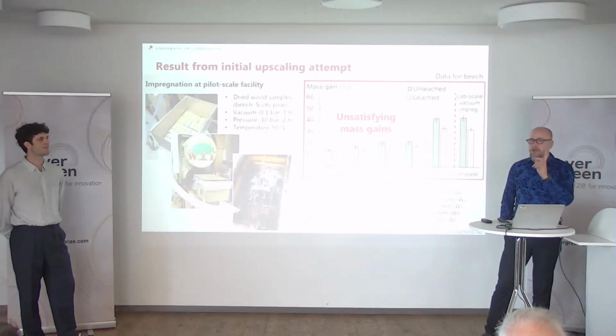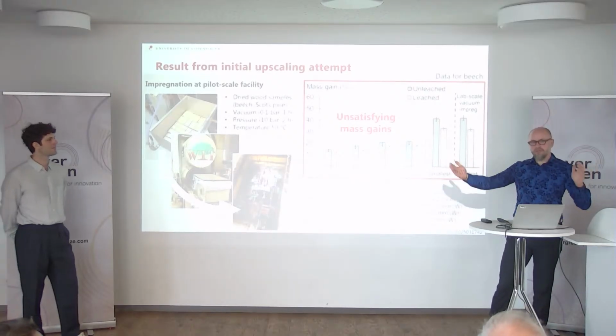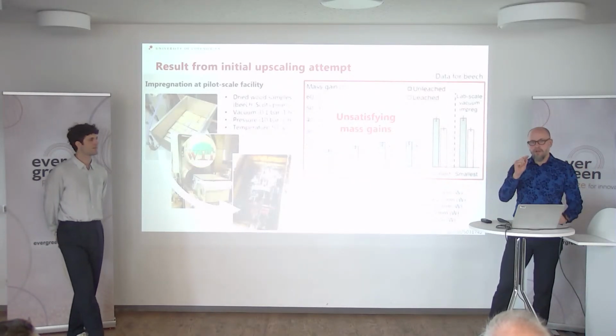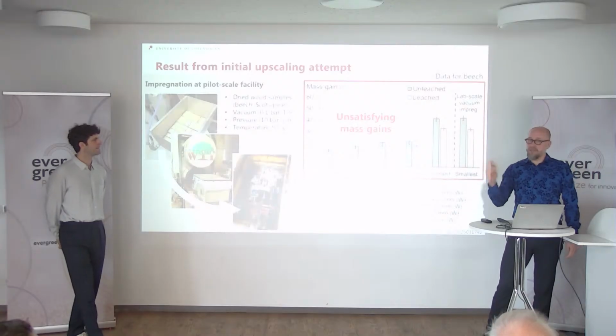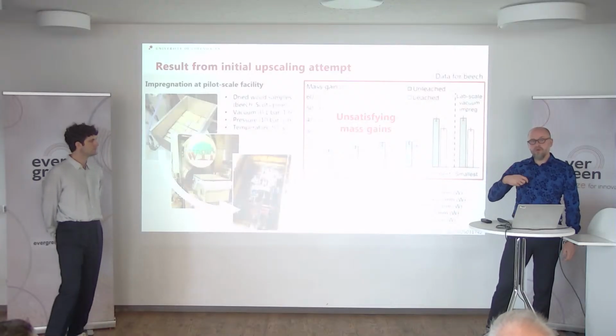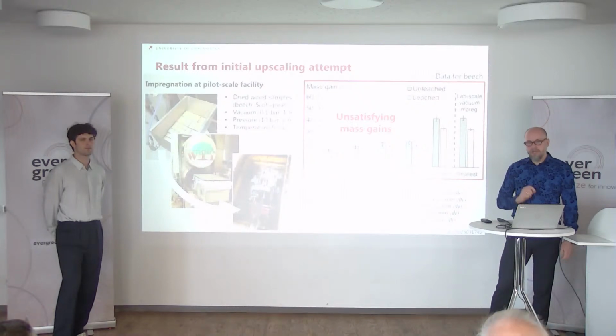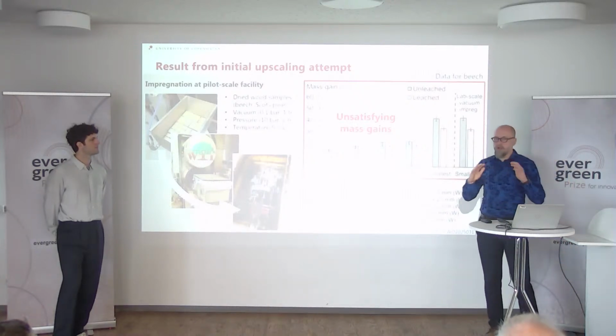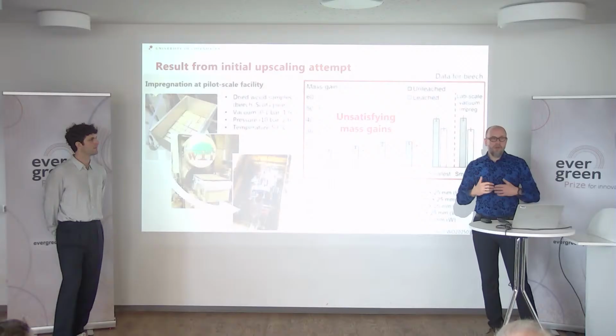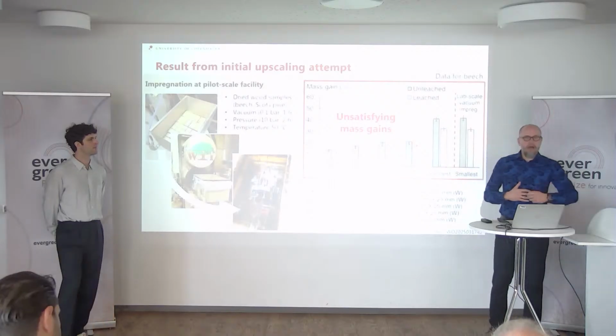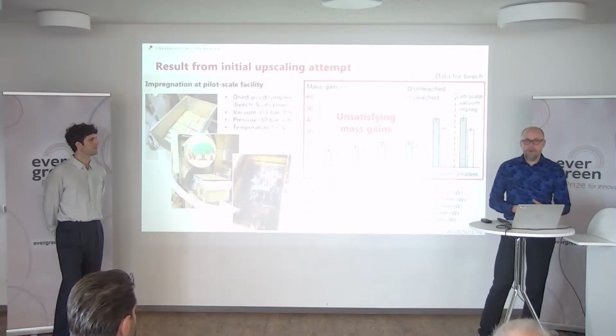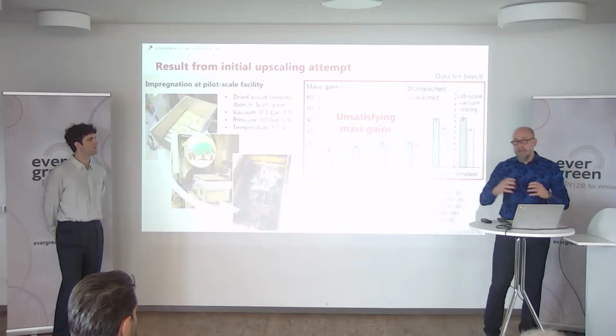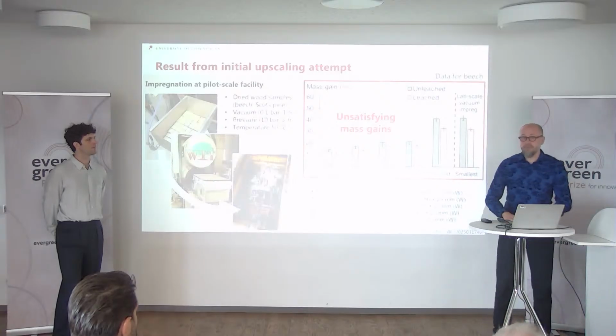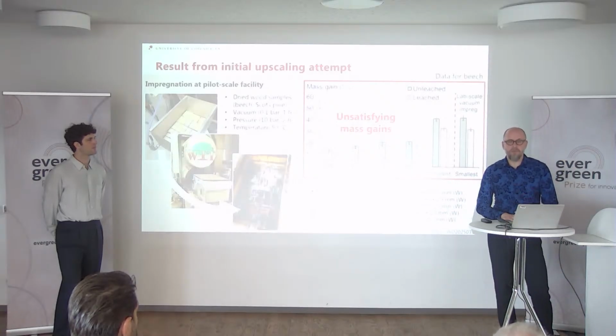Yes, you're right. But these super molecules, if you reduce the average size of the lignin molecules, you also decrease the viscosity. So there's also a viscosity component here. Okay. So we are trying out a lot of different formulations in terms of what's the solvent system, how can we improve the penetration by looking at both the lignin molecules as well as the solvent system itself in order to achieve good penetration.